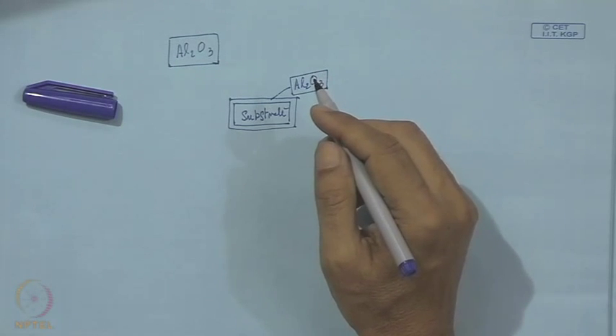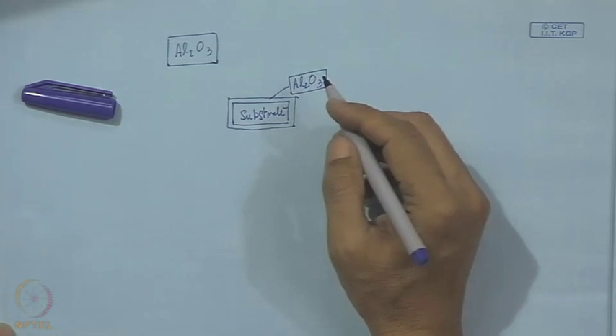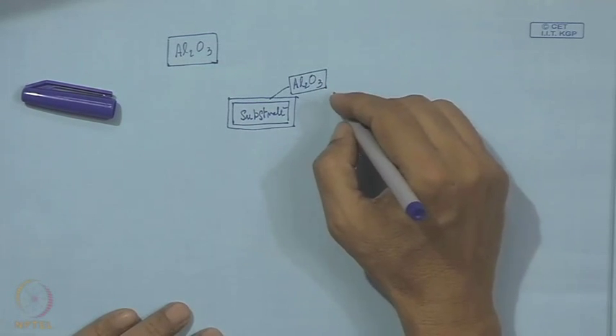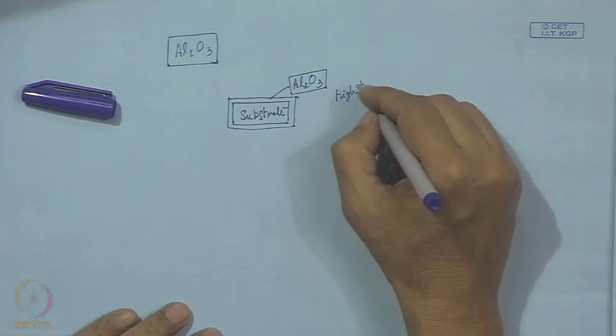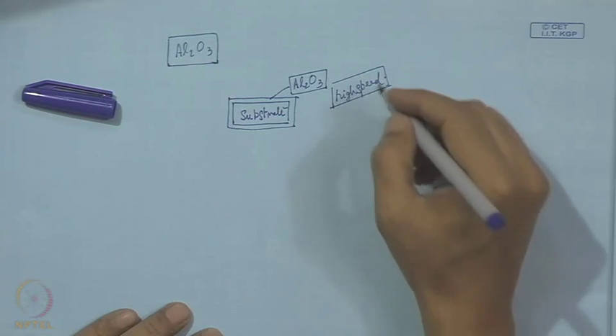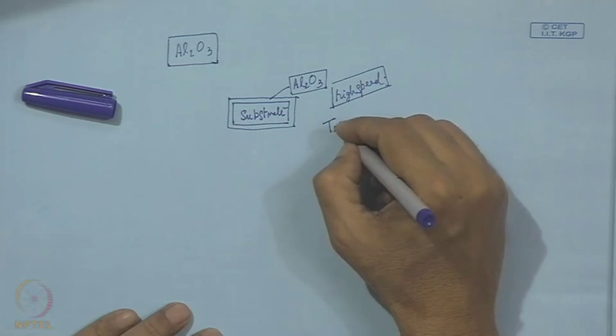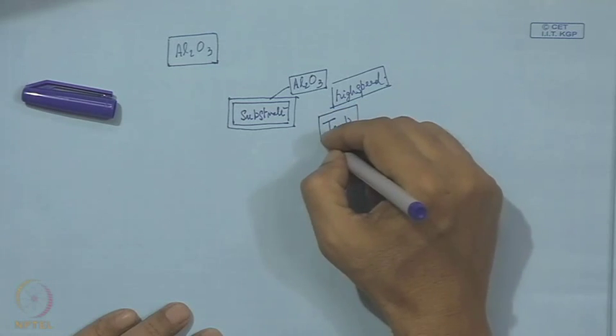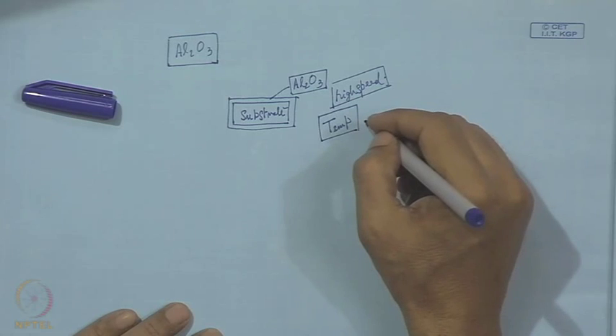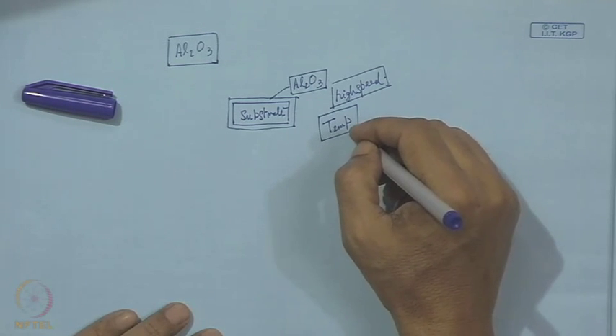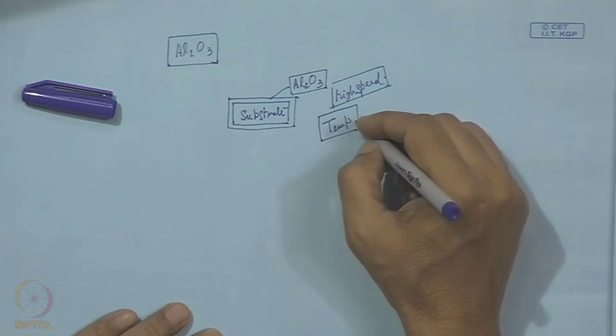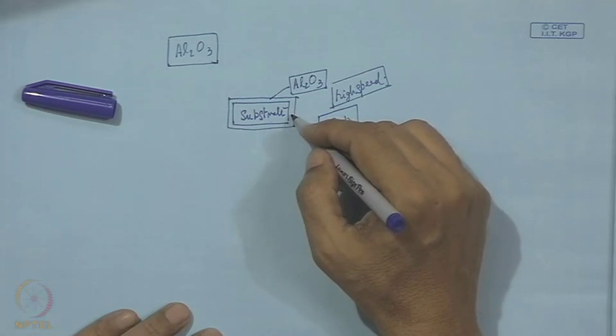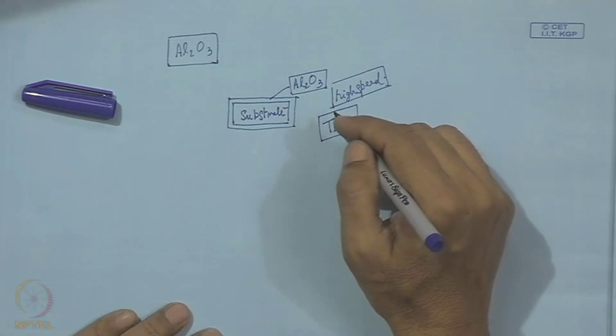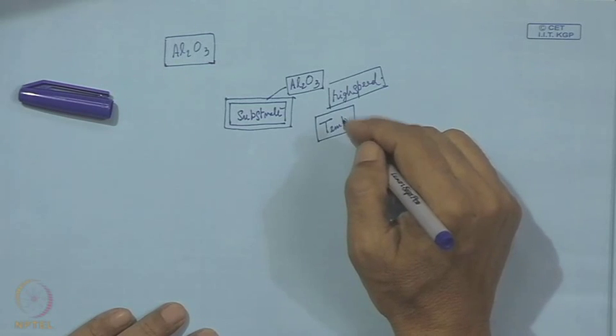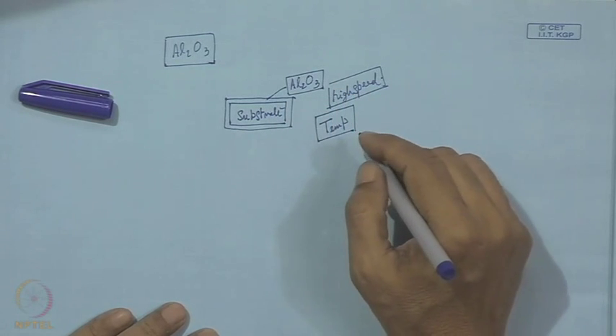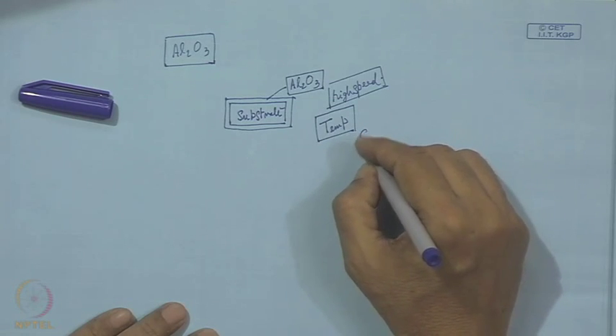Now, application of aluminium oxide as hard coating: when we go for high speed operation, this high speed is associated with high temperature, and it is actually the wear on the tool which matters most rather than any other mode of failure. And in this respect, the material at the top of the tool surface needs some very special characteristics which can reduce its wear rate, and that is exactly what we know as chemical stability.